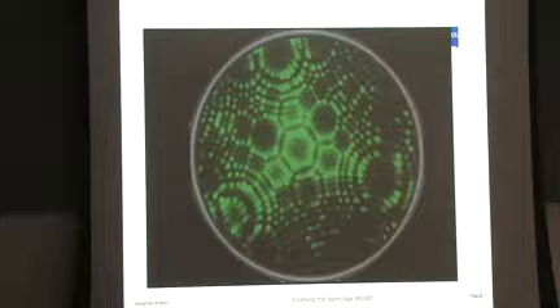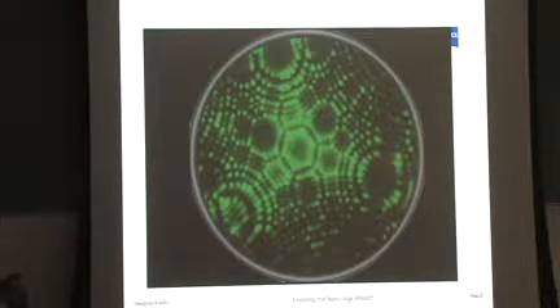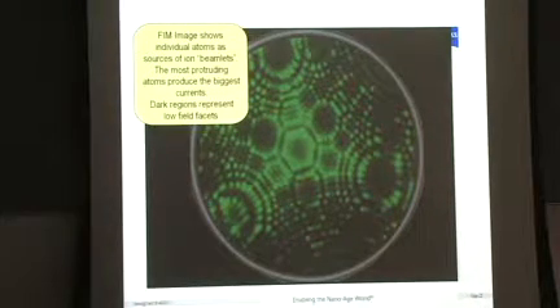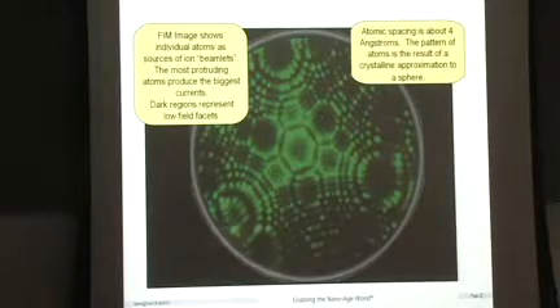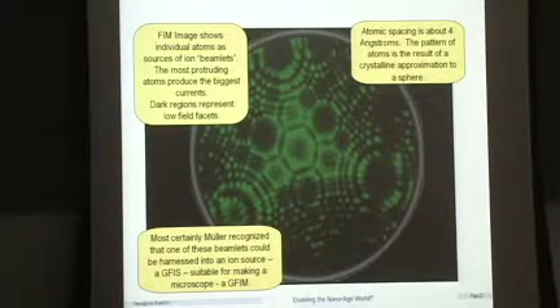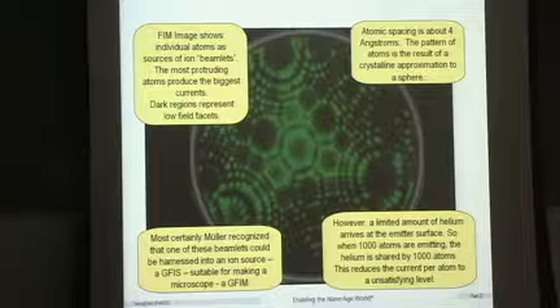The ionization is happening at each of these sites, and so therefore one of the rules of electron optics is if you start with a very small source, you can actually focus it back down to a comparably sized probe size. So this means that we can get an atomic sized probe out of this technology, and this is why a lot of those researchers I mentioned earlier were pursuing it so vigorously. It was not really practical at this point.